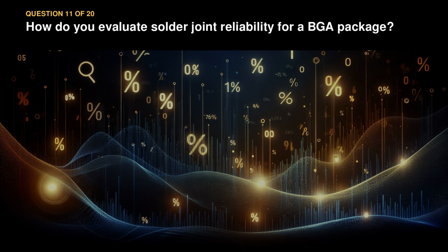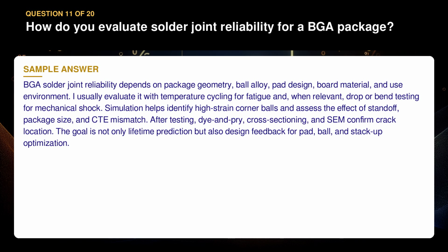Question 11. How do you evaluate solder joint reliability for a BGA package? BGA solder joint reliability depends on package geometry, ball alloy, pad design, board material, and use environment. I usually evaluate it with temperature cycling for fatigue and, when relevant, drop or bend testing for mechanical shock. Simulation helps identify high-strain corner balls and assess the effect of standoff, package size, and CTE mismatch. After testing, dye-and-pry, cross-sectioning, and SEM confirm crack location. The goal is not only lifetime prediction, but also design feedback for pad, ball, and stack-up optimization.